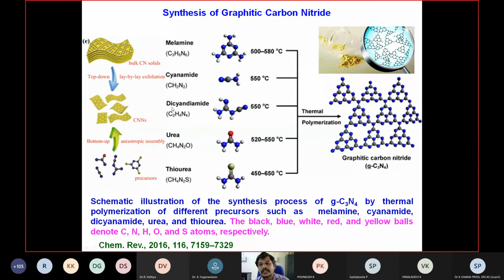The graphitic carbon nitride can be synthesized by using 2 different methods. The first method is the top-down approach. You take the bulk material, you exfoliate, then you will get thin-layer graphitic carbon nitride. Likewise, in the bottom-up approach, you take a molecular precursor, then it is subjected to pyrolysis followed by a polymerization process. You will end up with heptazine-based graphitic carbon nitride. You can take any precursor, melamine, cyanamide, dicyandiamide, urea, thiourea, anything, then just pyrolyze at the decided temperature, and you will get this.